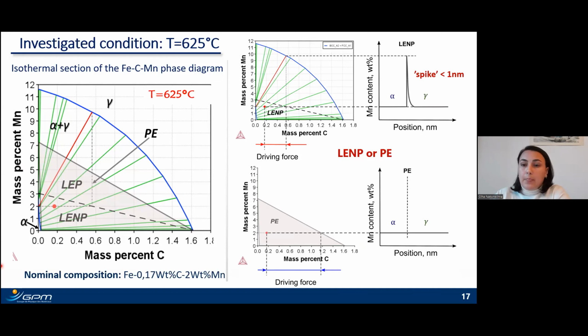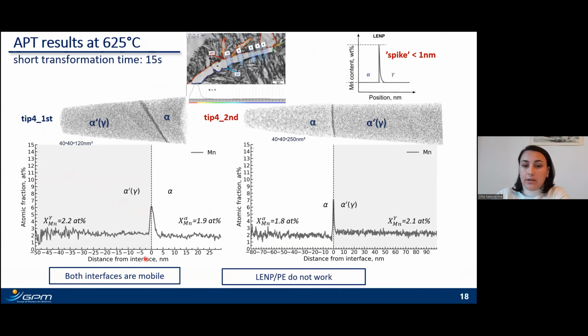At this transformation temperature, we obtained approximately 40 successful results. But since we observe a similar shape of the manganese profile for most of these results, there is no reason to show you many similar profiles. So on the next slide, I will show you just an example of the observed manganese profile at this condition. On the slide, you can see the 3D reconstruction and compositional profile across both the first and second interface of tip 4 shown here.